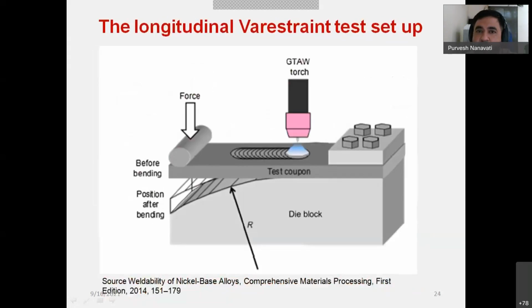Now we'll move further. This is the longitudinal Varestraint test setup in a 3D picture. You would see a GTAW torch, which is moving from this end to this end. Now you see the arc is in action, and this plate is fixed at one end using a fastener, a simple bolt, on the top plate, and this die has a particular radius. The mechanical force will be applied as soon as it reaches the predetermined location, and under the effect of force, this plate will be bent on the die, and you have seen the rest. This region will be taken for the study.